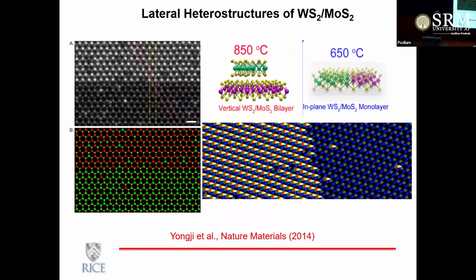So imagine at a single atom thick level, you are joining these insulating material and conducting material in plane laterally. Then we also started to think that there are many materials that are isostructural. Even in the tungsten sulfide, molybdenum sulfide material that we saw, we could create the same kind of heterostructures laterally. And again, these are two different compositions, but same structure. The band gap is probably very similar, but not exactly the same. So we started to make these type of nanostructures as well.